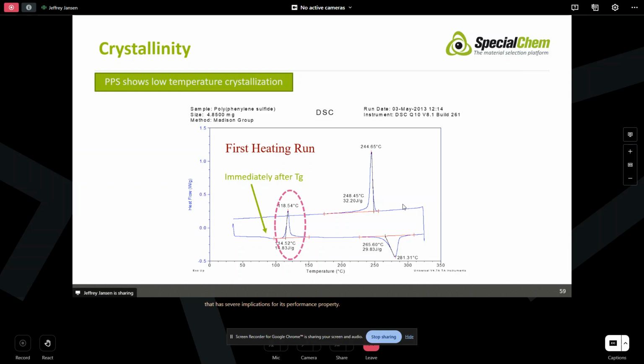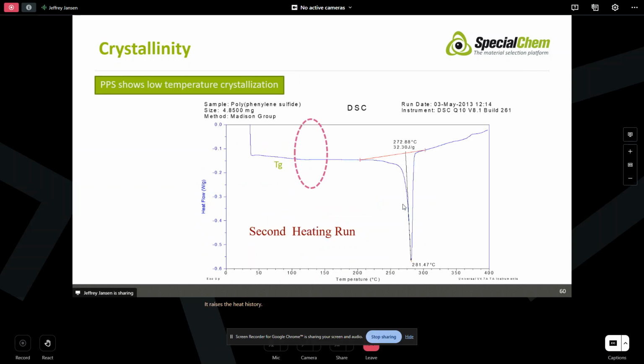So this is the first heating run and the cooling run. Again, it erases the heat history. When we come back and heat it again, because during the test we've control cooled it, we've allowed the material to become crystalline, we don't see that exothermic transition, right? All we see is that roughly 30 joules per gram associated with the melting of the crystalline structure that's there, okay? So again, now it'd be great if all polymeric materials had that exothermic transition, but only a few do.